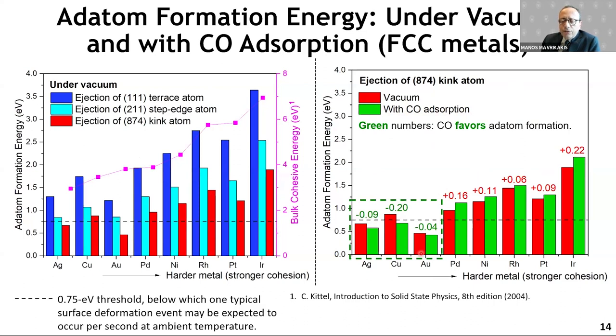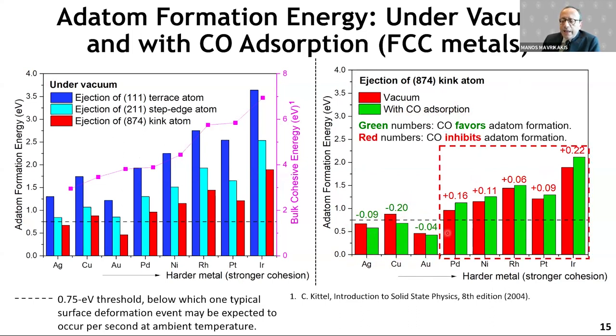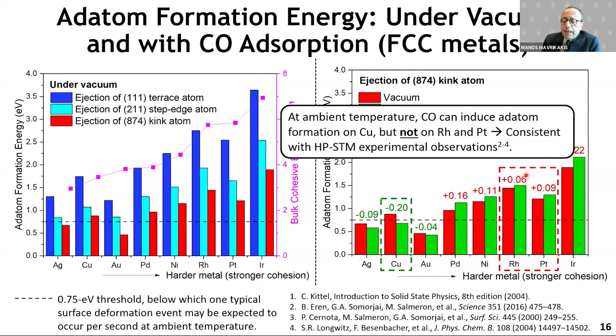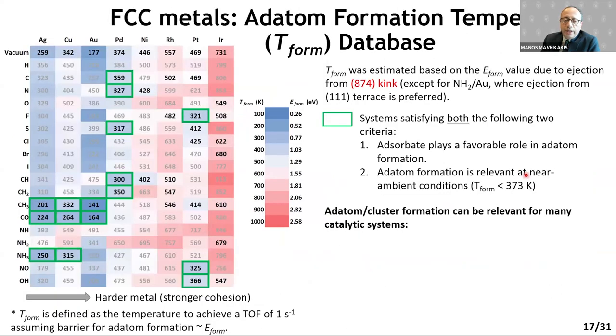So two classes of metals. One is the noble metals, the coinage metals. You see the green bar is lower than the red bar, which means the presence of adsorbed CO facilitates the ejection of metal atoms, whereas for the remaining non-coinage metals, the green bar is taller than the red bar, which means that CO decelerates or stabilizes the metal instead of helping eject atoms from it. This is actually good news if you go back to a slide where I presented experimental data on rhodium and platinum, where people could not really identify any cluster formation.